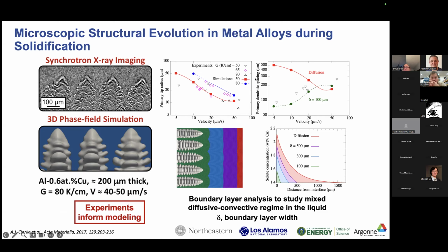That said, when we go to primary dendrite spacing versus velocity, the open points are the experiments, and in red are the first simulations that were done that ignore the impact of convection in the melt, and we get the wrong trend that doesn't match the data.